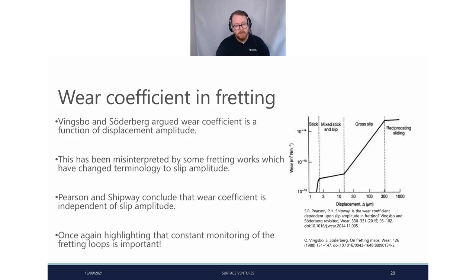Pearson and Shipway concluded that the wear coefficient is independent of slip amplitude, but of course this displacement amplitude still holds correct. So in stick, much lower wear. As we increase that displacement amplitude, we're increasing the amount of wear, increasing most over our displacement during gross slip and then into reciprocating sliding. So one of the things that is important with this, again, to highlight, whatever piece of equipment you're using, you want to make sure that it is able to monitor everything during the process,